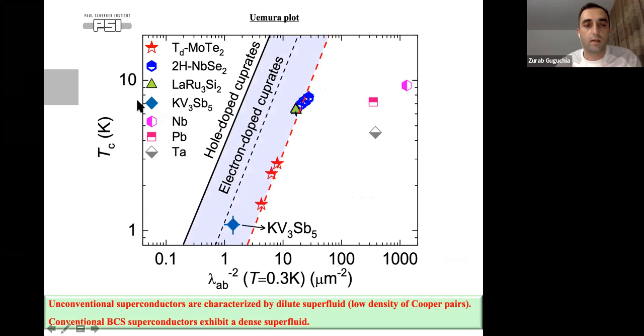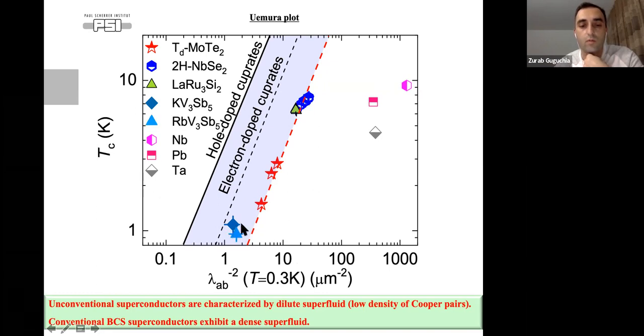The last slide is that, to compare the superfluid density of this material with other unconventional superconductors, I show this Uemura plot, where the conventional superconductors are far right on the plot. So they have large superfluid density and very small ratio. This material is very close to other unconventional superconductors like electron-doped cuprates or the semi-metallic superconductors, and this is again a kagome superconductor. So it's far away from the conventional superconductor state. This means that this system is characterized by dilute superfluid, so low density of Cooper pairs, and the same is true also for the rubidium compound.